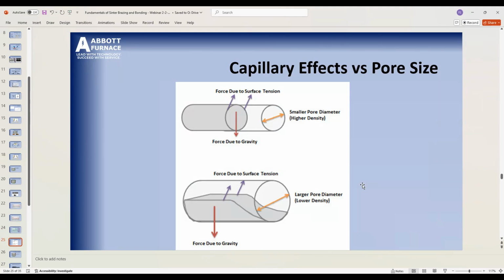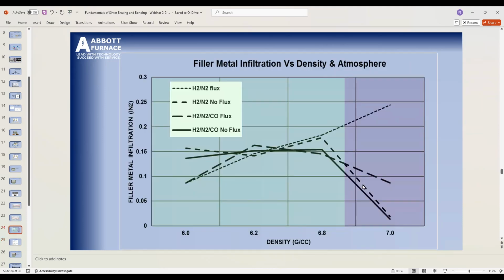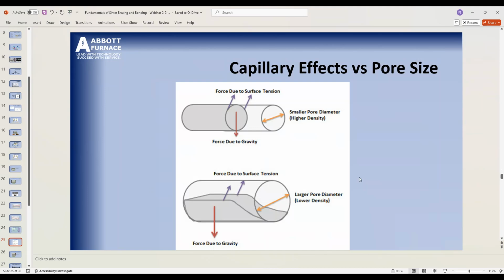Okay, and why do great big pores not work? Why do we lose control at 6.0, where we have big pores, low density? Because if I have a real low density, the pores are great big, and I don't have enough viscosity of that filler metal when it melts to fill the pore. It wants to fall into the pore and fill the bottom of the pore like it's a sewer. And so now the only thing that pulls that filler metal through is the contact with the pore surface.